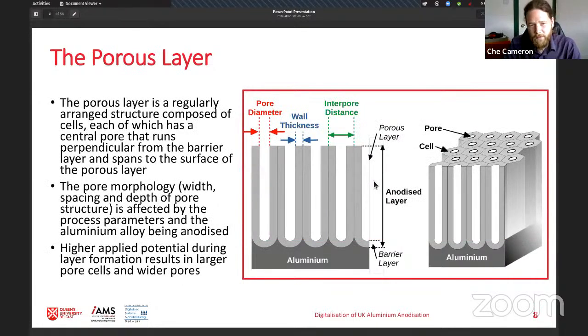Now, the porous layer, though, is the interesting part that gives a lot of different properties to an anodized finish. What it is, is a regular structure of hexagonal cells, and each of them has a pore that runs from the top of the cell down to that solid barrier layer of oxide. And when we speak about the porous layer in aluminium anodization, we talk about its morphology. So this is the width, the spacing, the depth, the shape of the pores.